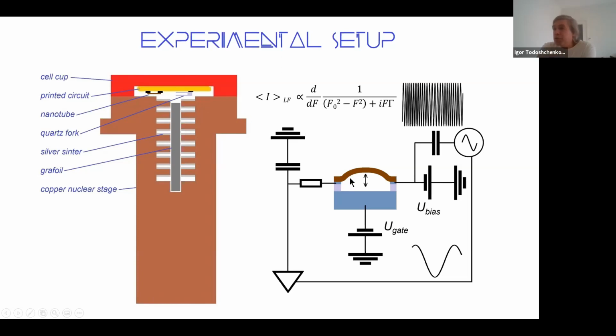So how do we measure it? This is a suspended nanotube, and we excite it with a high RF voltage. And this RF voltage is frequency modulated, as you can see. Because the carbon nanotube is not a linear element, because its resistance itself depends on the applied bias voltage, a low frequency component appears exactly at the modulation frequency. It has a usual Lorentzian shape, but differentiated with respect to the frequency, because it's not a direct measurement at high frequency, but frequency modulation. Here F0 denotes the resonance frequency, and gamma is the width of the resonance, or dissipation.